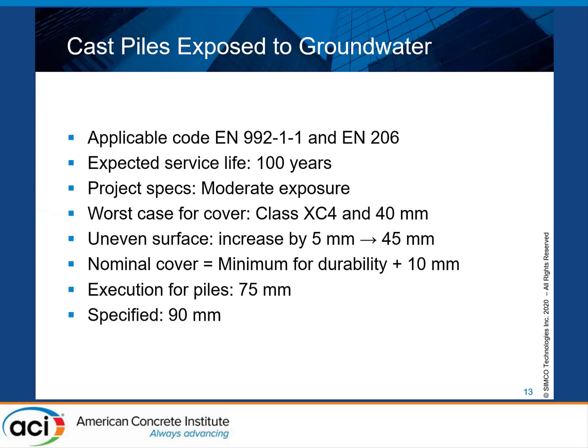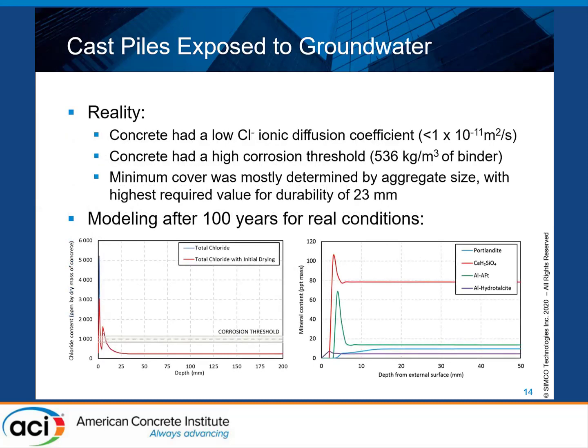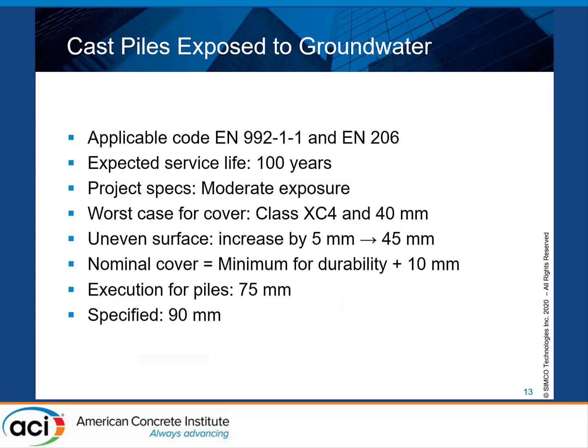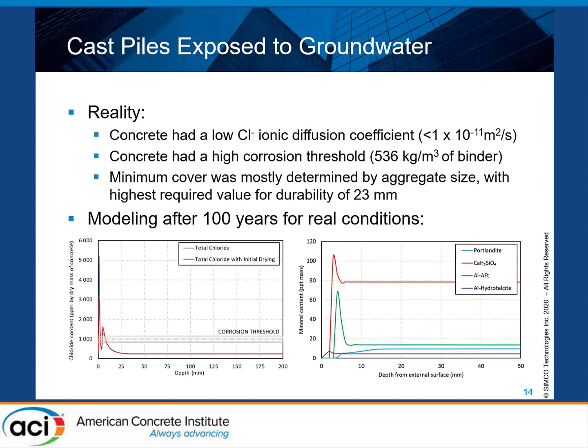If we convert it to the exposure classes, for the worst case, for that project, it was an XC4 and it required 40 millimeters of cover, but because of the uneven surface. Well, okay, I'm going to jump to show you that in that case, modeling after 100 years of real conditions, the cover requirement was 75 millimeters. What was specified was 90 millimeters, but I only needed 23 millimeters because the concrete was so good. It has a diffusion coefficient less than 1 × 10^-11 square meters per second, and a high binder content, so a high threshold. So the real cover was much less than required. So we got a much better performance than if we were just following the code.